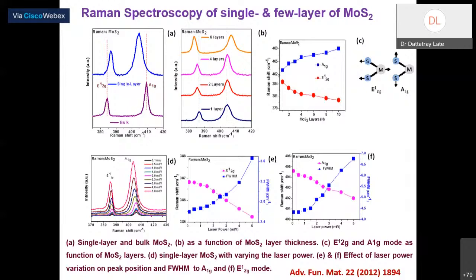Again, here Raman spectroscopy becomes very powerful. Raman spectroscopy also tells you the thickness of MoS2. An important thing to note is that after 10 layers, MoS2 behaves like a bulk. Up to 10 layers, it is in the nano region. After 10 layers, it becomes like bulk MoS2 material.